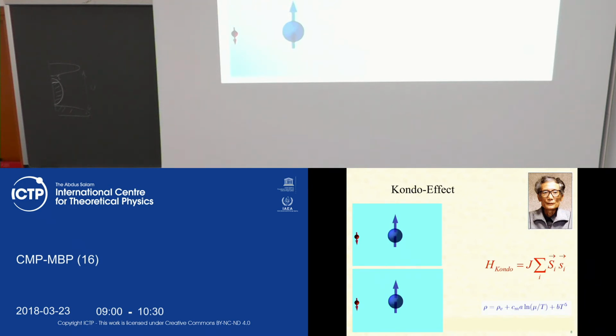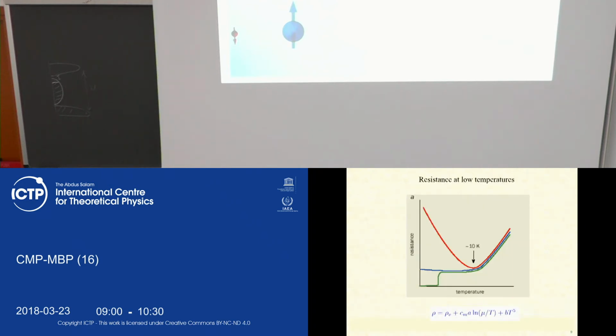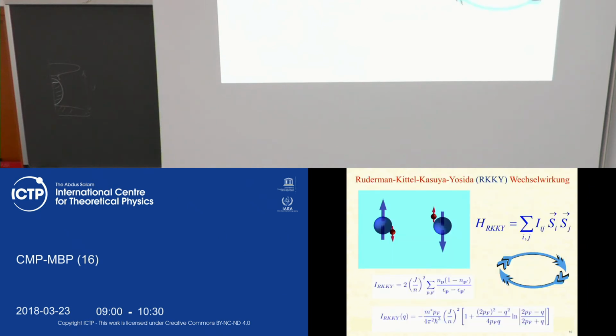So an increase of resistivity when the temperature is lowered is an absolutely counterintuitive effect, because we are used to the fact that either resistivity drops and forms a superconducting state, or resistivity saturates at some residual value and stays flat. Here the resistivity increases, and Kondo proposed the mechanism which explains this increase of the resistance. So this is what I said is typical. The green curve is for superconductors. There is some critical temperature after which resistivity drops to zero. A typical example is mercury.